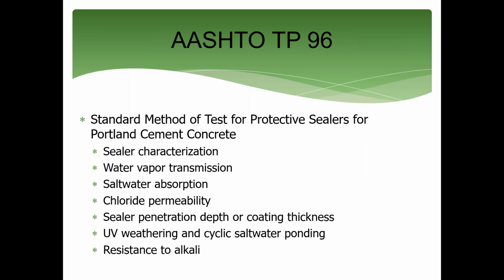The task force chose to use AASHTO TP96 as the backbone of the new concrete coatings and sealer work plan. Due to its successful use by other agencies, it was considered a tried and tested methodology from which to build our work plan. TP96 includes the following testing parameters: sealer characterization, water vapor transmission, salt water absorption, chloride permeability, sealer penetration depth or coating thickness, UV weathering and cyclic saltwater ponding, and resistance to alkali.